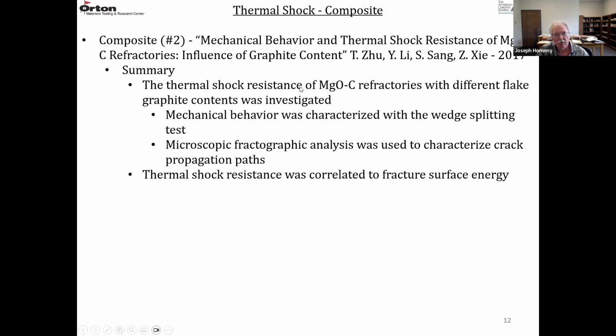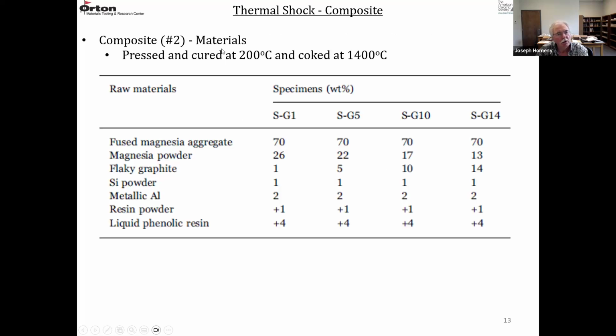So the thermal shock resistance of an MgO carbon refractory was investigated at different flake graphite contents. They used the wedge splitting test to get the fracture surface energy. And then they did some fractography to characterize the crack propagation paths. And then the thermal shock resistance was correlated to this fracture surface energy that's measured by the wedge splitting test. So there were several specimens here as a function of graphite content.